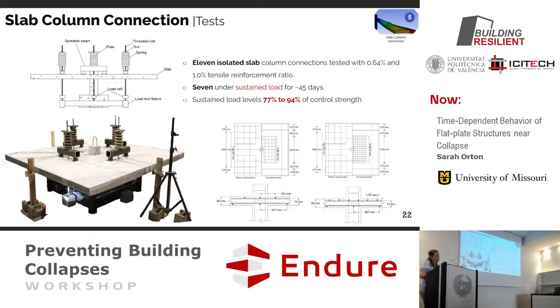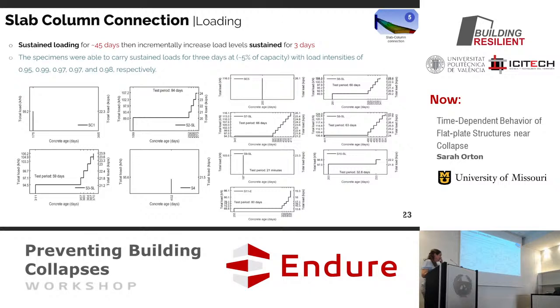Last set of tests we did was these isolated slab column specimens. So you have your reinforced concrete slab here, and then you have the column in the center. The slab was, I think, 3.5 inches, 89 millimeters. Just typical reinforcement, nothing really too special about it. It did extend beyond the inflection point. This is where the inflection point would be in the real structure, and I extended it beyond it so that you could include any compressive membrane effect that would be used in the slab as well.